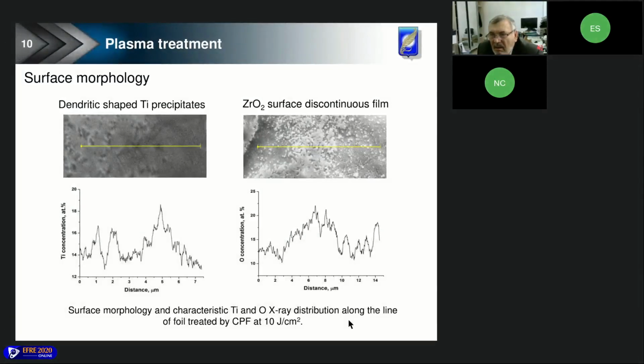Here you can see small dendritic-shaped precipitates with the approximate size of 1 micrometer or less. Elemental analysis showed that these precipitates were enriched with titanium. That correlated with the results of phase composition analysis that revealed alpha titanium crystalline phase appearance. Here, a thin oxygen-containing discontinuous film can be seen. According to the data of the phase composition analysis, this film contained 2 polymorphic modifications of zirconium oxide.